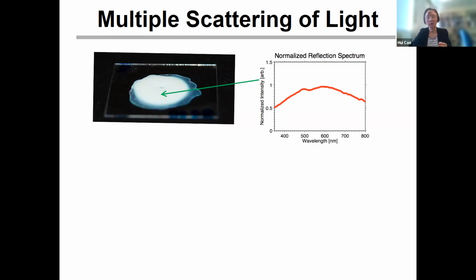The reason is because, as we said, the short range order will make the blue color reflected first, right? Because it enhances the reflection of the blue ones. But if the sample is too thick, the red color or other colors can still be scattered, but have to travel a longer distance before they can be reflected back. So if the sample is thick enough, at the end, all the colors can be reflected back. Maybe blue will start first, but all others can be reflected. So that means we cannot get this kind of color.